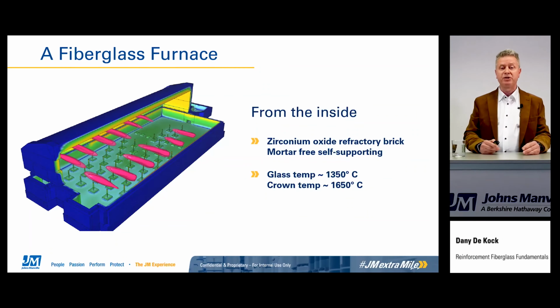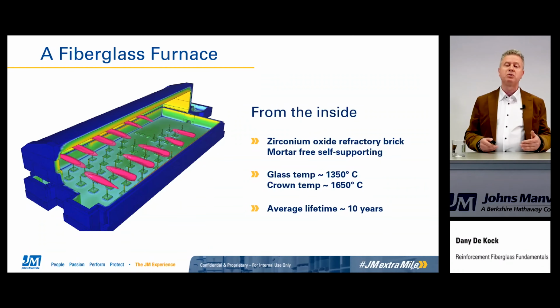So, like I said, the glass is molten at a very high temperature. It's 1350 degrees C, more or less. But the oven temperature, the top of the roof, the crown temperature, is about 1650 degrees. So this refractory brick needs to resist high temperatures. And we cannot run a furnace up and down. When it starts to run, we need to run it for about 10 years. What is the average lifetime of a furnace? We try to do it more, of course, when there is no damage, and the damage is most often coming from the side walls. The side walls are getting thinner all the time because of the abrasiveness from the glass fiber, taking step by step thin layers away. And when this side wall becomes too thin, then we need to start our rebuild.